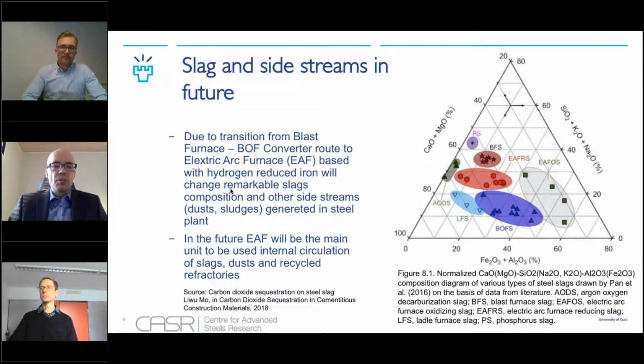But it's not only the reduction process which will be changed, but also the slag and side streams will change in composition because of the transition from blast furnace BF route to electric arc furnace. If hydrogen reduced iron is used as raw material, it will dramatically affect the slags and dusts and sludges which are generated in a steel plant.